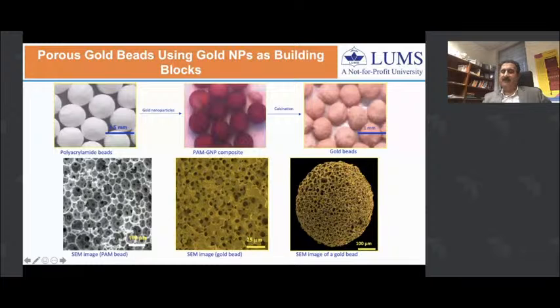So this is 99% gold, pure gold, and you will see that these gold beads retain the emulsion templated porous structure of these polymer beads. So in this way, we were able to reproduce the emulsion templated porous structure of polymer bead into emulsion templated porous structure of these gold beads that have decent surface area.